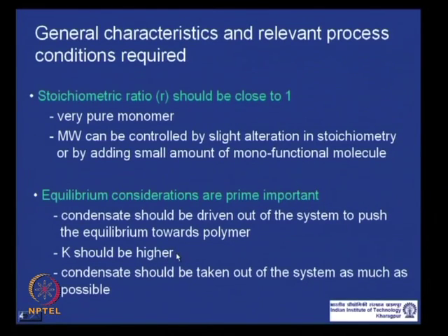Now, what happens if you have a higher K? For a given polymer, for targeting the same polymer molecular weight, you can actually live with a small amount or a larger amount of condensate in the system. If you compare two reactions, one having a higher equilibrium constant, then in that case you can build that high molecular weight, leaving a little excess amount of the condensate.